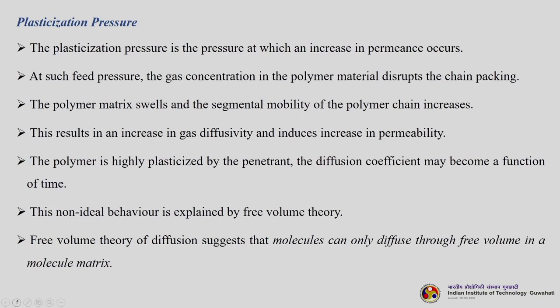Then plasticization pressure. Plasticization pressure is usually defined as the pressure at which an increase in permeance occurs. At such feed pressure, the gas concentration in the polymer material disrupts the chain packing. The polymer matrix swells and the segmental mobility of the polymer chain increases. This results in an increase in gas diffusivity and induces an increase in permeability. The polymer is highly plasticized by the penetrant. The diffusion coefficient may become a function of time. Now, this non-ideal behavior is explained by the free volume theory. Free volume theory of diffusion suggests that molecules can only diffuse through free volume in a molecular matrix. So, this is the free volume theory.